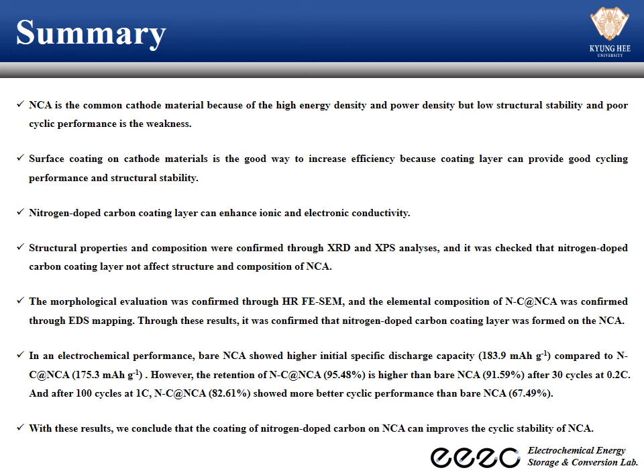Through these results, it was confirmed that a nitrogen-doped carbon coating layer was formed on the NCA, and in electrochemical performance, bare NCA showed higher initial specific discharge capacity compared to N-C@NCA. However, the retention of N-C@NCA is higher than bare NCA after 30 cycles at 0.2C rate, and after 100 cycles at 1C rate, N-C@NCA showed better cyclic performance than bare NCA. So, with this research, we conclude that the coating of nitrogen-doped carbon on NCA can improve the cyclic stability of NCA.